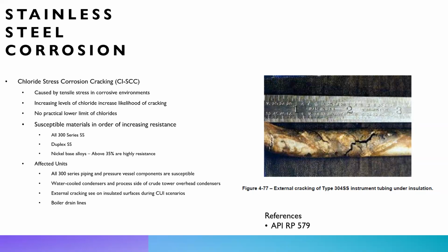So susceptible materials, in order of increasing resistance, are going to be all your 300 series stainless steels, your duplex, and even your nickel-based alloys, but these are going to be the most resistant. So any nickel-based alloys with more than 35% are shown to be very resistant to chloride stress corrosion cracking. So any of your 300 series piping and pressure vessels are going to be susceptible. You're going to see this more in your water-cooled condensers and process side of your crude tower overhead condensers.